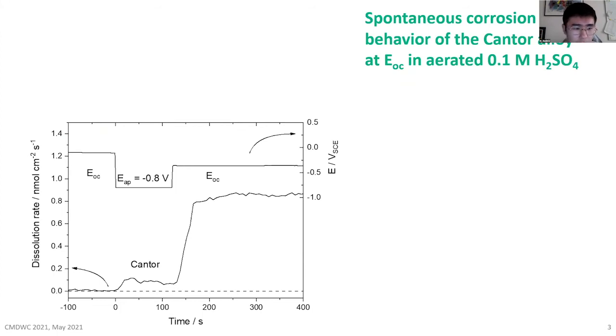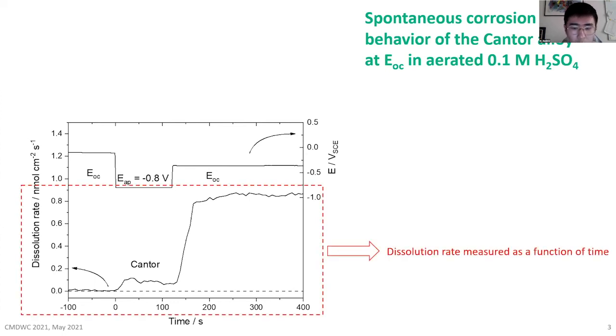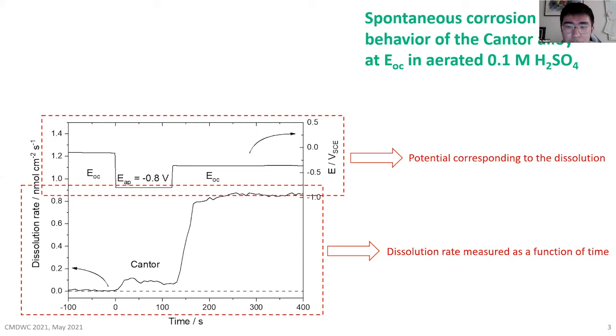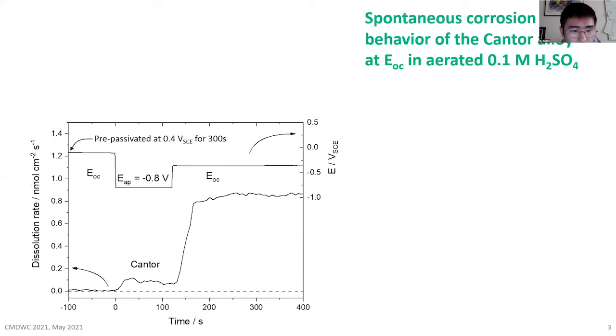So this figure is the first result. There are two parts to this figure. In the lower part, we show the dissolution rate measured as a function of time. It's the sum of the elemental dissolution we measured by AESEC. And the upper part shows the corresponding potential. Please note that this alloy was pre-passivated at 0.4 volt prior to the experiment. So we can see that for the first step at the open circuit potential, we detected very little dissolution because the alloy was in a passive state.